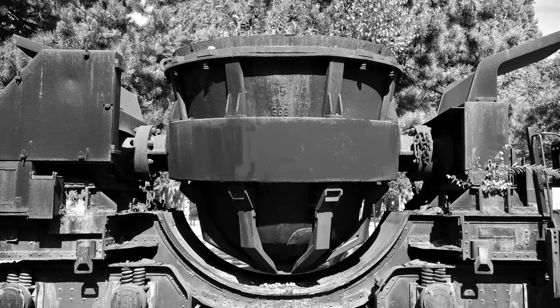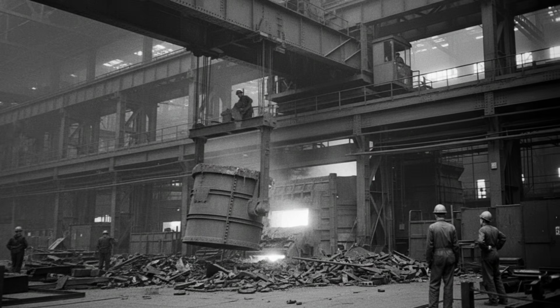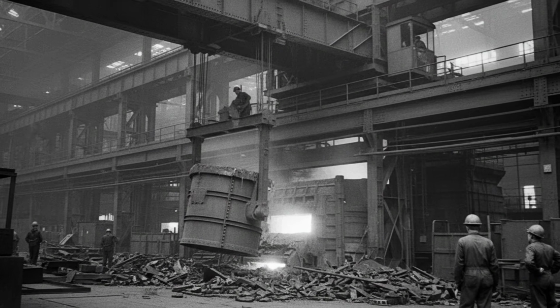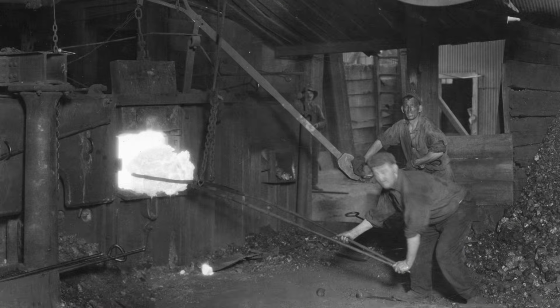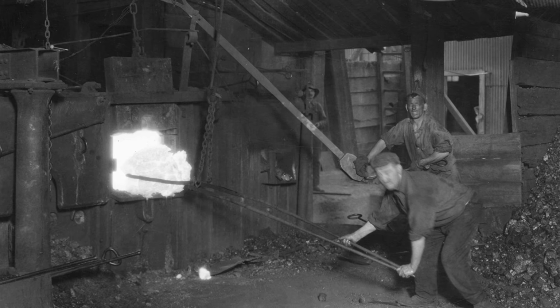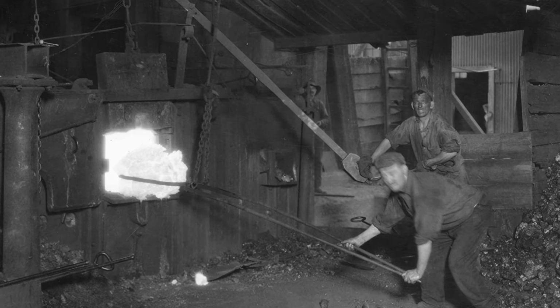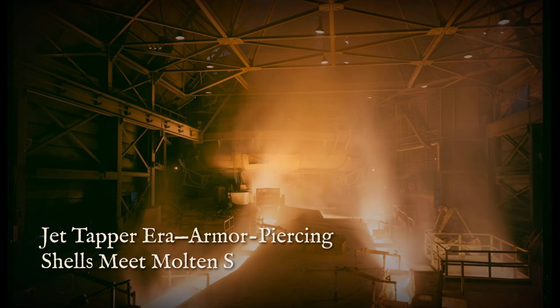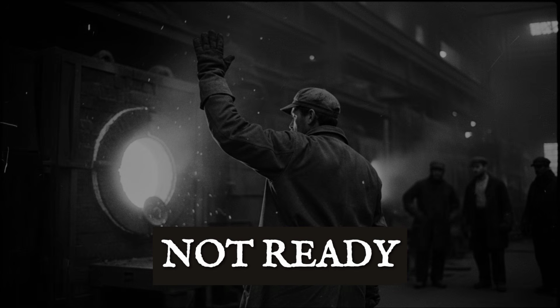The ladle, waiting in the pit below, held the tap. If the ladle was in position, if the crane operator had it correctly placed, if the refractory lining of the ladle was preheated and dry, the tap was routine. If any of those conditions was not met, the tap was not routine. There is an account from Bethlehem Steel, documented by a man who worked in the Open-Hearth shop there, of a furnace ready for tap and a second helper signaling that he was not ready to open it.